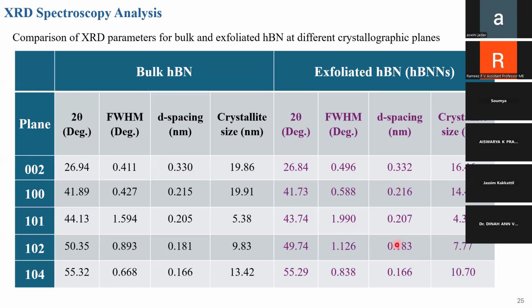So again, I want to tell you that the d-spacing is increased, the FWHM is increased, and the crystallite size is decreased. These are the important parameters you can visualize during exfoliation, which can be seen in XRD outcomes.